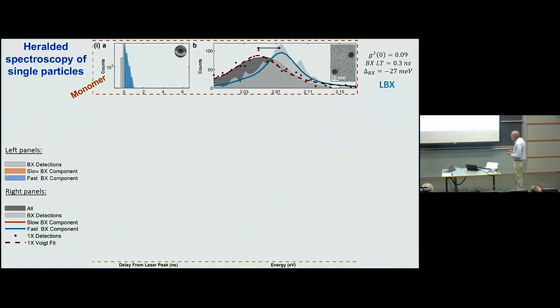And so this is a bit elaborate, so sorry, but this is the typical result of a single particle. These are all the photons, which are dominated by the single photon emission in this case. And now these are the first photons in the pair of the monomer, the first photon in the biexciton, and you see this is very clearly blue shifted. Blue shifted because in this system, this is a quasi-type 2, we call it. Namely, the electron is spilling out, the two electrons are spilling out, the holes are localized. So the repulsion between the two electrons and the two holes is overcoming a possible attraction.